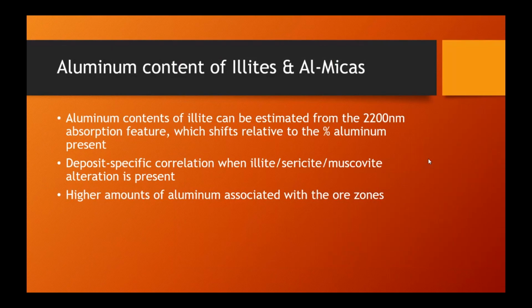So another perspective of this shift is the aluminum substitution of illites and aluminum micas. Aluminum content of illite can be estimated from the 2200 nanometer absorption feature, which shifts relative to the percentage aluminum present. There appears to be a deposit-specific correlation in that when illite, sericite, muscovite alteration is present, there are higher amounts of aluminum apparently associated with the ore zones.